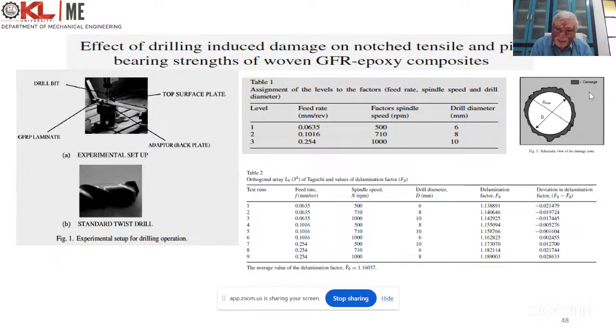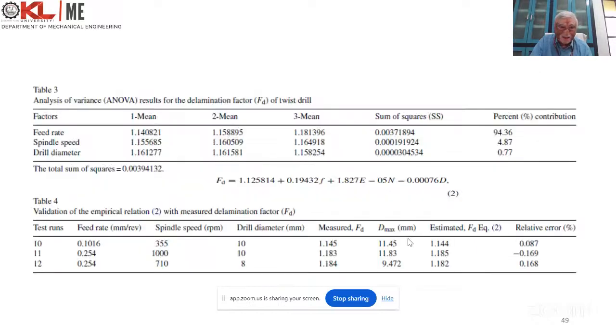Here, the process parameters for drilling are feed rate, spindle speed and drill diameter. 3 parameters are there, and 3 levels we have fixed. Strictly speaking, we require 27 tests, 3 into 3 into 3. But when we apply the Taguchi design of experiments method, we require only 9 tests, and we can predict 27 test results. So that is the beauty of the Taguchi method. From the analysis of variance, the feed rate shows a percentage contribution of around 94%. The spindle speed is 4%, and drill diameter shows 0.77.